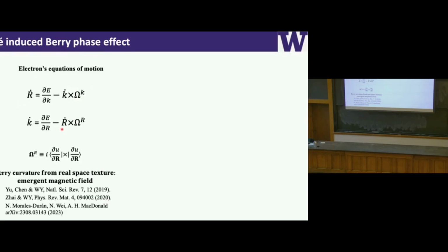Then we look at the second equation. The first term is r-dot, which is the velocity v, right? And the second is Omega_r, the Berry curvature in real space. Then you can consider it as velocity times a pseudo-magnetic field. If we just apply a real magnetic field in the system, we know v cross B is a Lorentz force, which will give rise to the Hall effect. But in this case, we don't have a magnetic field. What we have is the real space Berry curvature, Omega_r, which is written down by this equation here.